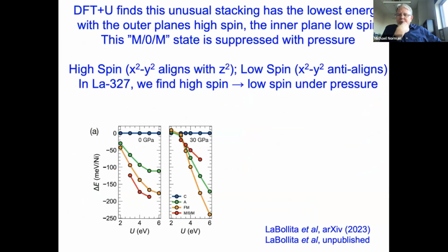In very recent work that Harry did with Antia, surprisingly, he found that this so-called M0M state, where you have the outer layers antiferromagnetically polarized and the inner layer non-polarized, is actually the lowest free energy state. It was very surprising. There's a tendency for a high spin state, where the x squared minus y squared orbitals are aligned with the z squared, or a low spin state, where the x squared minus y squared orbitals anti-align with the z squared orbitals. What seems to be happening in 327 is that as you go up in pressure, you drive from a high spin to a low spin state, whereas you automatically get this in the trilayer, where the outer layers behave like high spin and the inner layer behaves like low spin. And again, under pressure, you're probably driving the outer layers into a low spin type state. At least this is what seems to be going on.